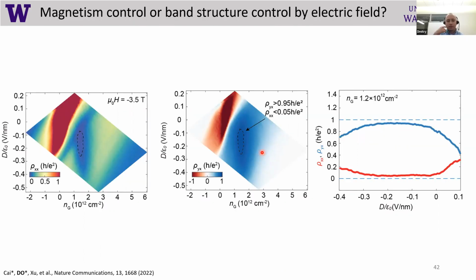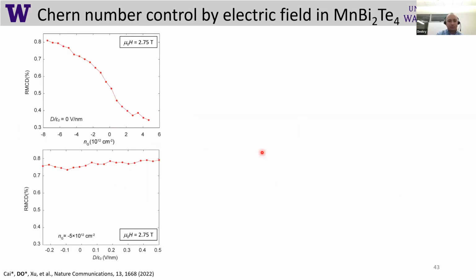And in this case, the question comes essentially what this electric field does. Does it control the band structure itself, or does it control the magnetic state? To look at it, we did extensive studies measuring RMCD, so magnetic circular dichroism, which informs us on the magnetic state of the system, at different electric fields and different gate voltages. So our conclusion is that our electric field doesn't affect magnetism too much. This is the bottom plot. When we sweep electric field, essentially the magnetic state stays the same.